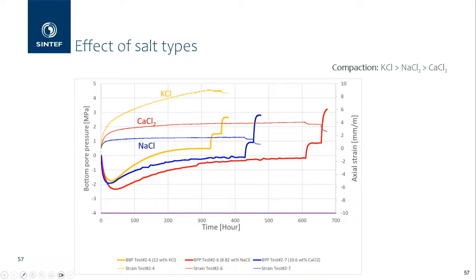So the compaction is very little, and surprisingly, calcium chloride also has a compaction. But theory says that it shouldn't, because the calcium ion is bigger. When it moves in, it should actually expand a little bit. But the experiment didn't confirm that. But KCl, which is most important, confirmed that the compaction is much higher when you have KCl, because the potassium ion is small, and the lattice space in a smectite, which has a double layer of water, which we call bound water, along with free water in the middle, likes K, the potassium ion. It moves in, kicks the sodium out, and shrinks. And that's why the shrinkage is higher for KCl.